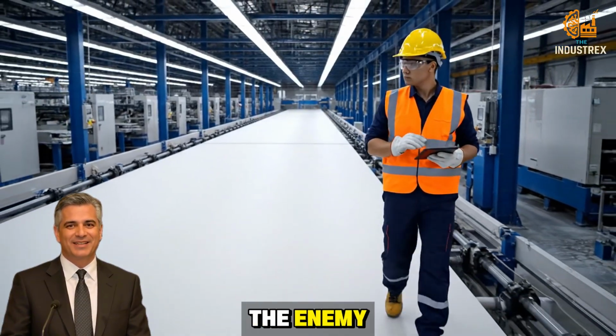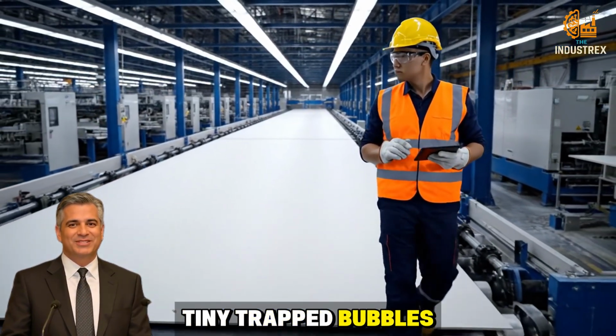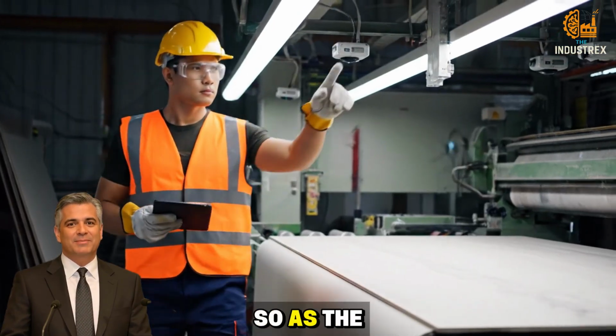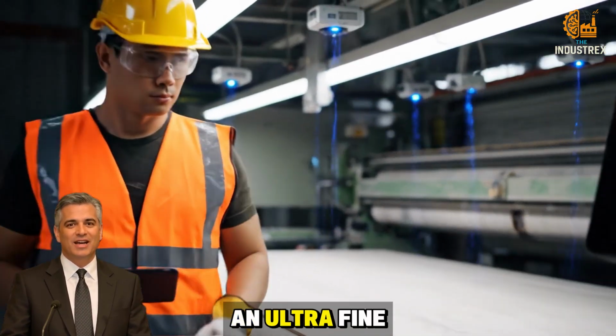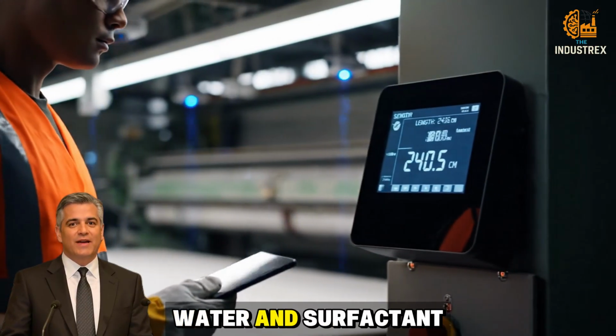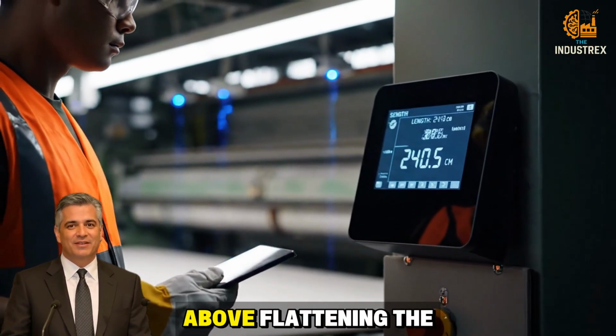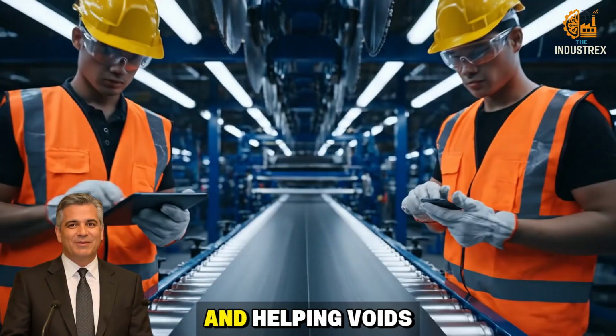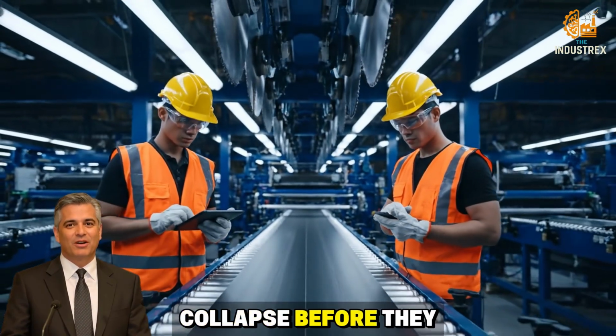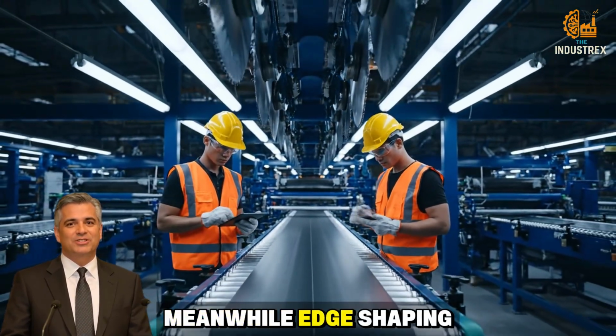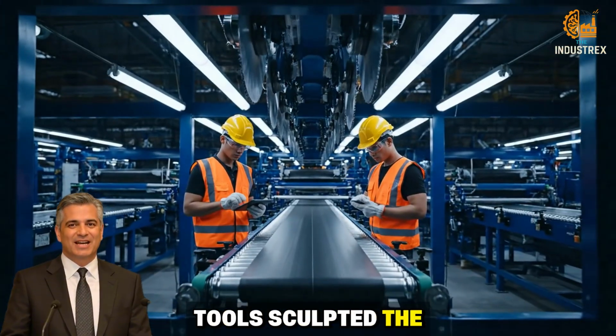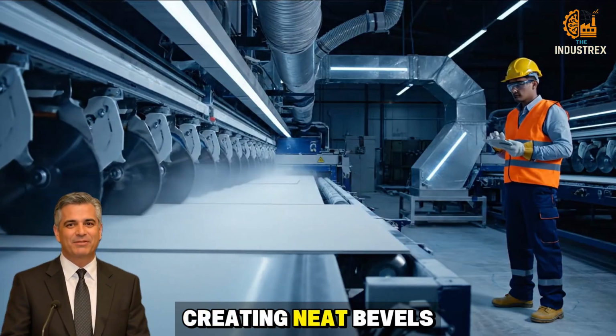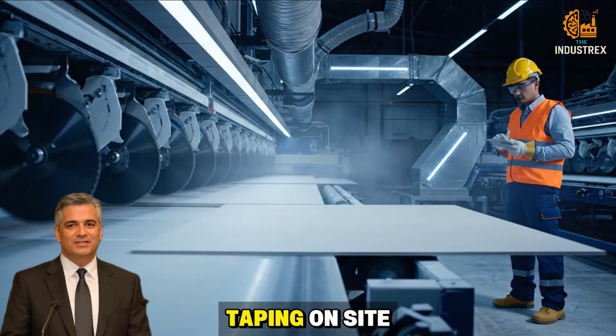But air is the enemy. Tiny trapped bubbles can create weak points. So as the panel sets, an ultra-fine mist of deionized water and surfactant is sprayed from above, flattening the surface and helping voids collapse before they harden. Meanwhile, edge-shaping tools sculpt the side profiles, creating neat bevels for easier joint taping on-site.